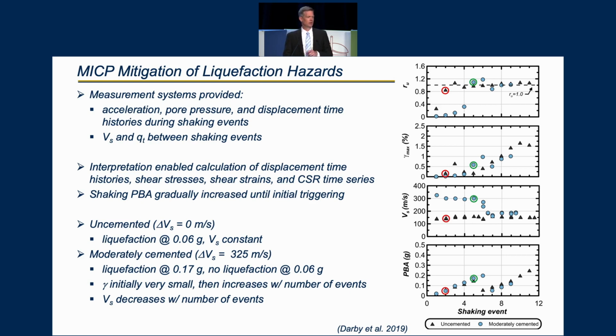First of all, I want to note the uncemented characteristics are in the triangles, and the moderately cemented conditions are in the blue circles. The uncemented model liquefied with only about 0.06 G shaking, and as we would expect, without cementation, the shear wave velocity didn't really change before or after shaking, and this has been commonly observed. On the other hand, the moderately cemented material did not liquefy until a shake of about 0.17 G, and on top of that, we could also see from shear wave velocity that there was some damage to the cementation and it began to degrade.